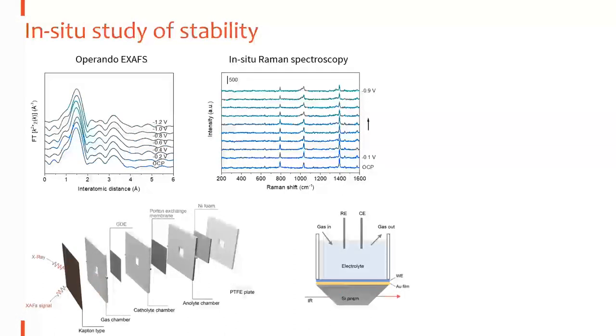So we sought to use additional spectroscopic methods to do in situ measurements to prove the stability of our material. Our first approach is in situ Raman. All these peaks are related to the copper BTA molecule. We found that at different applied potentials, we did not observe the disappearance of these peaks. Of course, copper does not have a Raman signal, so we cannot detect the copper. This is easy to understand.